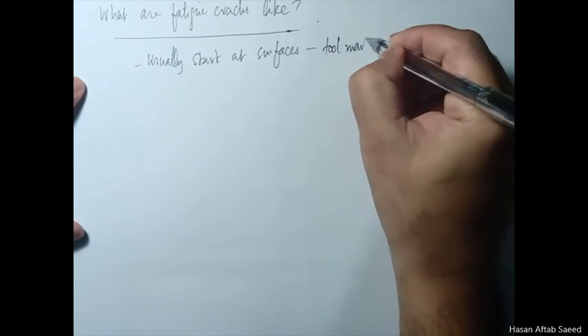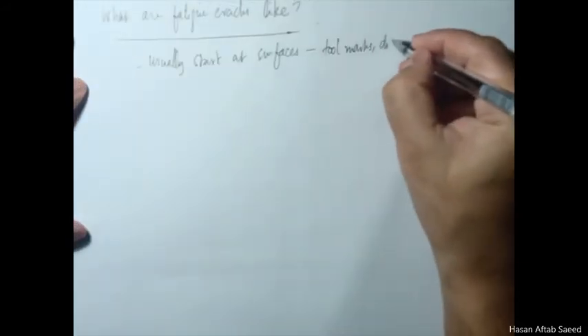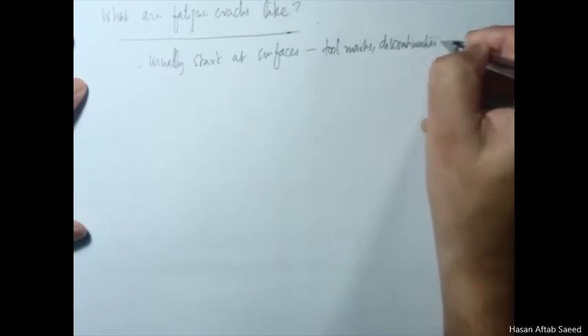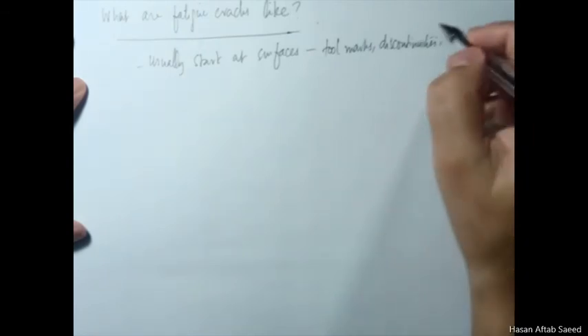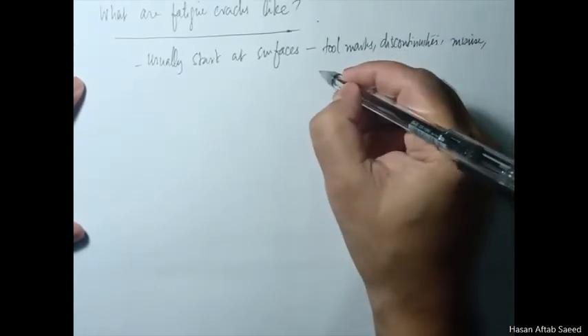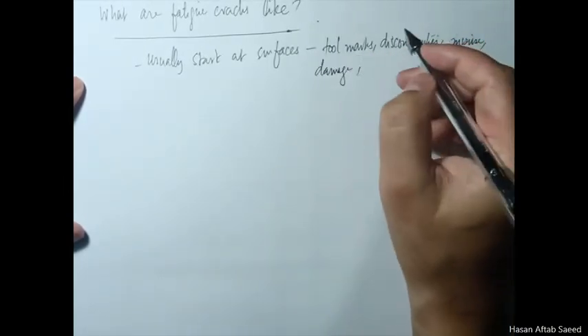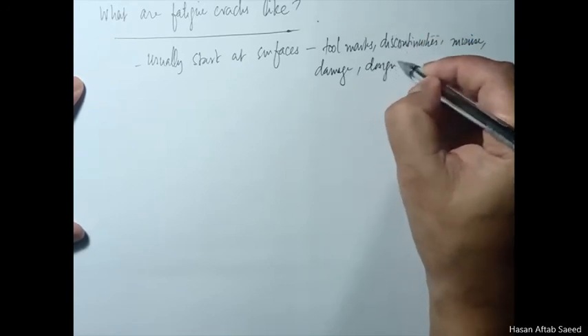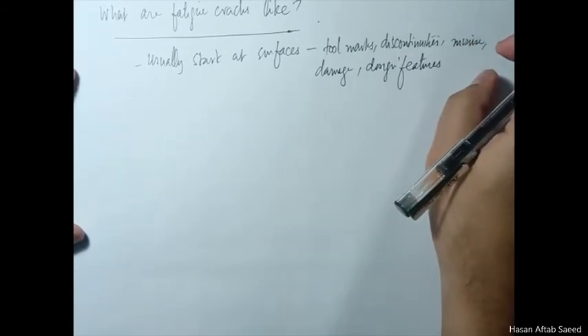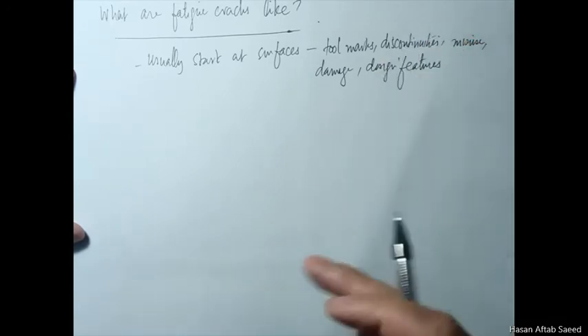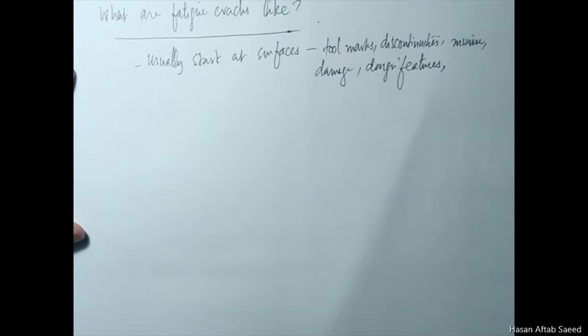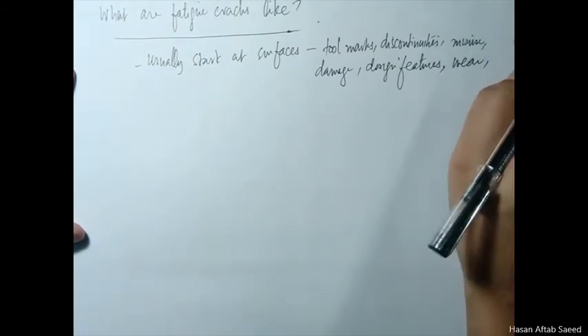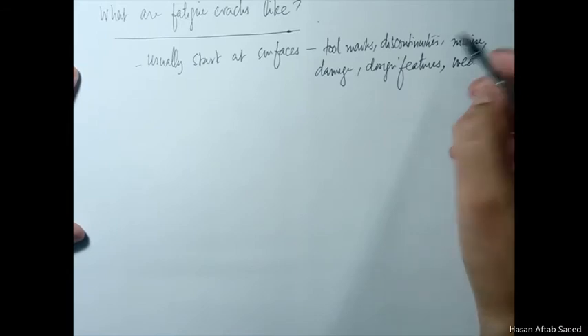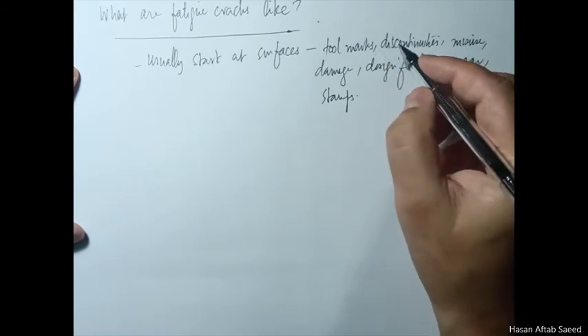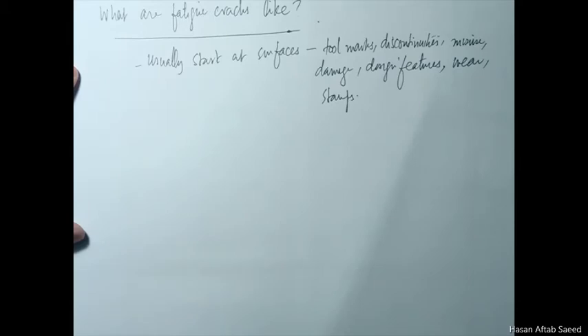Because of tool marks, discontinuities, any sort of discontinuity, and misuse, yes, damage. Most of the damage occurs at the surface. Design features, for example, there's a key. You are going to use a key, then there will be a keyway, and the keyway will have a certain corner. So these design features are unavoidable for design. So wear, it could wear. There are cracks that start from the effects of wear. There could be stamps. You apply a stamp, and it could start a crack. So mostly they start at the surfaces, although there are exceptions.